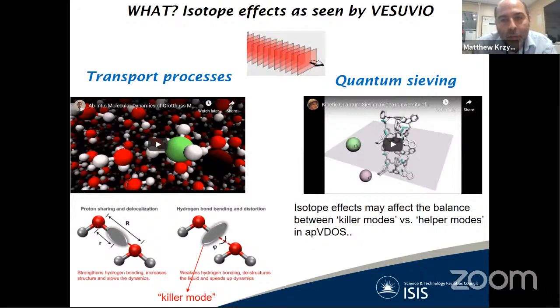As we know, quantum sieving occurs for hydrogen and deuterium in organic porous materials when the difference between the linear size of the hydrogen and deuterium molecule is more or less in the range of the thermal de Broglie wavelength. And due to the interplay of this thermal de Broglie wavelength and the geometric constraints, we have kinetic quantum sieving. So Vesuvio would be very well equipped to measure selectively the amounts of zero-point energy broadening of hydrogen and deuterium adsorbed in a system like this as a function of temperature and gas adsorption.